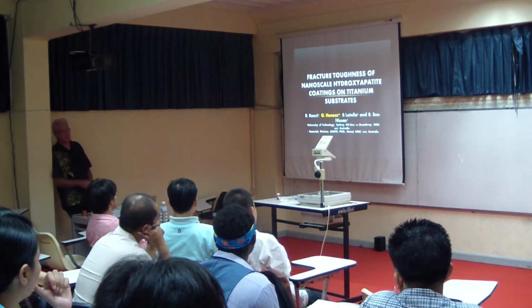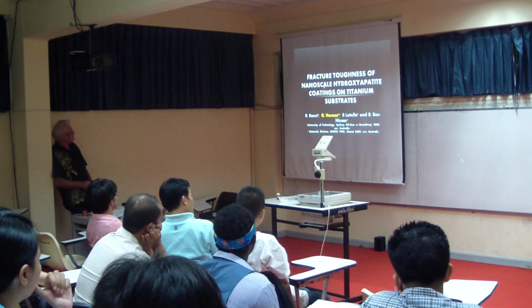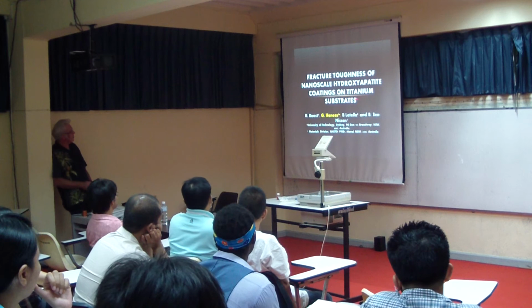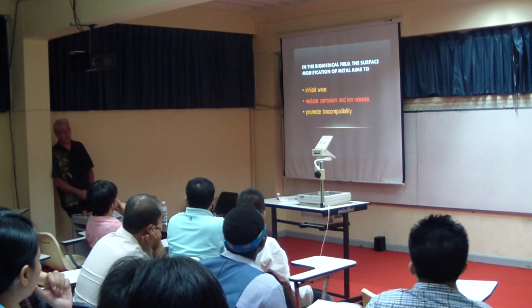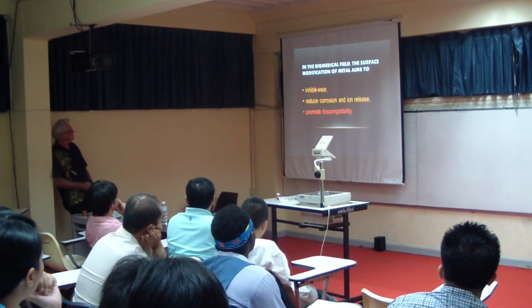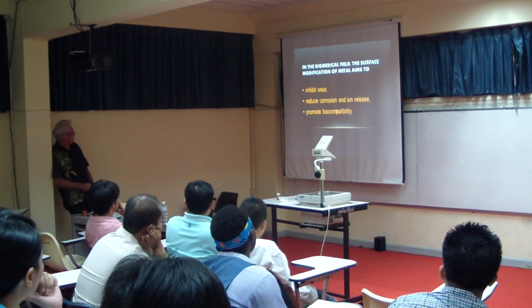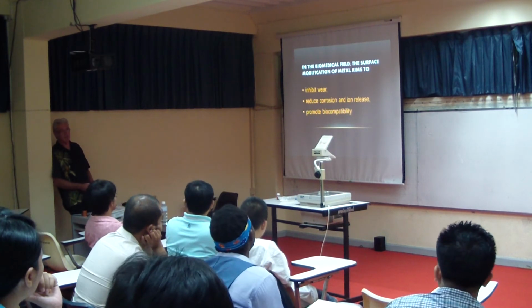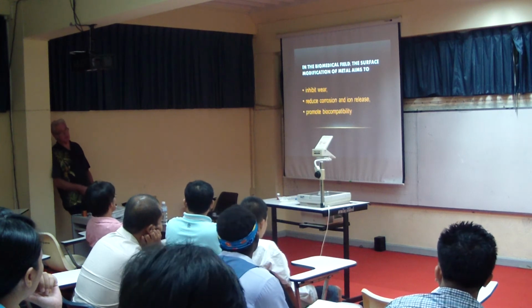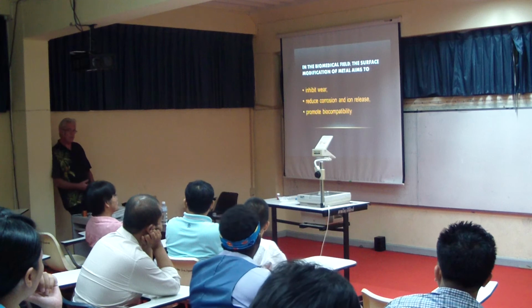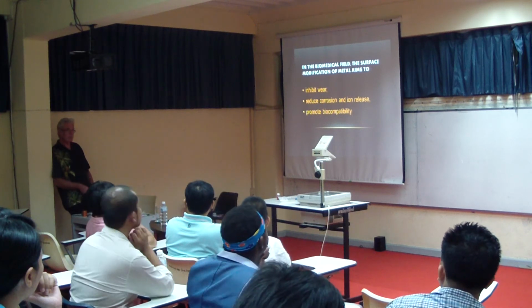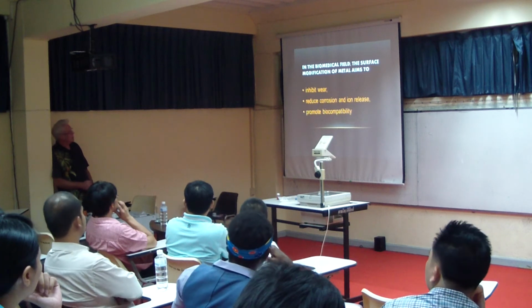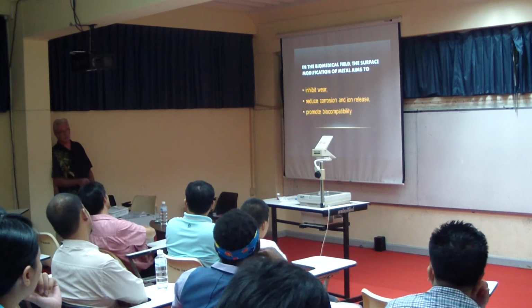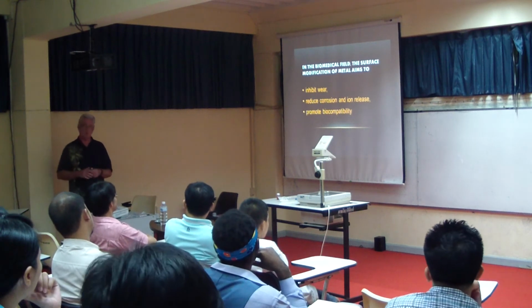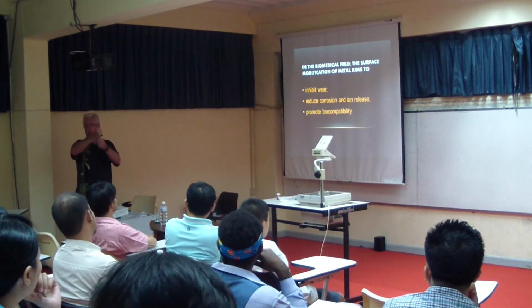So I'm just going to give a couple of examples of some research reports. In this case, we have nanoscale hydroxyapatite coatings on titanium substrates. Why did we do that? Well, it's for biomedical application. And what we wanted to do is inhibit wear, reduce corrosion, and promote biocompatibility. Titanium, while it's very good, it will still corrode in the body. And it's also very hard to get bone to stick to it. So the concept was that if we put hydroxyapatite coating on the surface of the titanium and it was porous, the bone could grow into the coating and hold it.